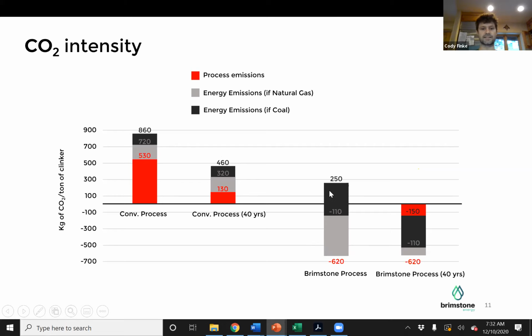Now, with our process, we start with carbonation of the waste magnesium. So if we use natural gas as energy source, just the carbonation at the plant gate is already negative 110 kilograms of CO2 per ton of cement. For coal, we're a little bit positive at 250 kilograms of CO2 per ton of cement. However, our cement, again, being the exact same cement, will still carbonate. And over a 40-year lifetime, we will suck the same amount of CO2 out of the atmosphere, in which case both coal-fired and natural gas-fired cement will have a lifetime negative emissions.